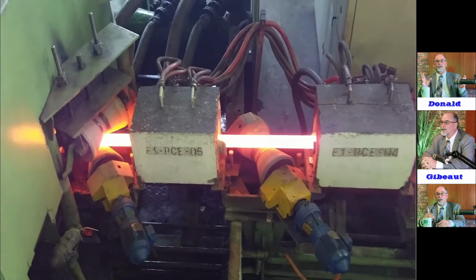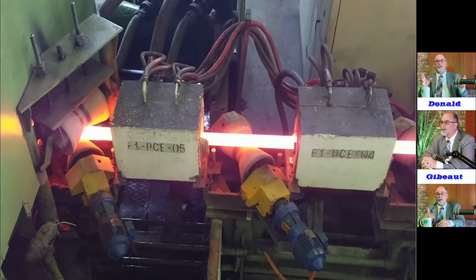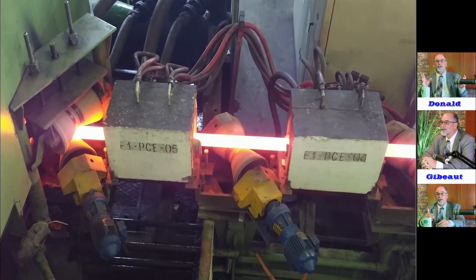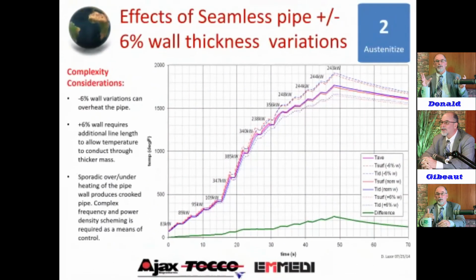So again, proof in the pudding there, so to speak, showing you, not just telling you. This is seamless. We talked about the L80 and the P110 and the upset effect, but there's also a condition with seamless. Traditionally, seamless has been all run on furnaces because API allows a very broad variation in the wall thickness. And that variation equals additional hooks in the pipe.